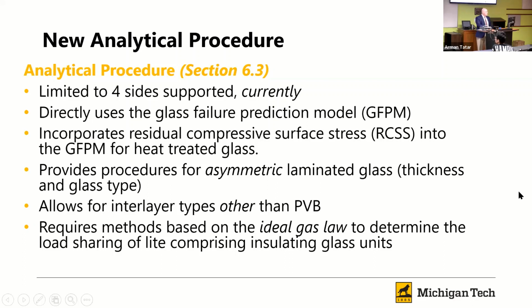So for a couple of reasons I'll mention a little bit: it was limited to 4-side support glass. And it does directly let you use the glass failure prediction model, which I'm going to show you a shortened version of in a second. And then we also allowed, instead of just using a simple factor of 2 and 4 for different heat treatment types, you can measure the residual compressive surface stress of heat-treated glass, and you can use that directly.